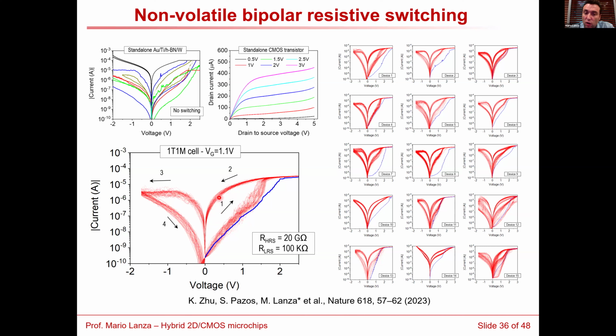Now we have a low resistive state. And then when we apply a negative ramp, we observe that the conductivity decreases, and we observe a current level that is similar to before. So basically, this thing is showing non-volatile bipolar resistive switching. But now is different than the case before in the large devices.